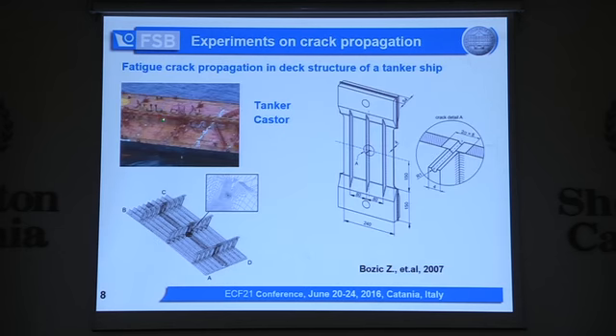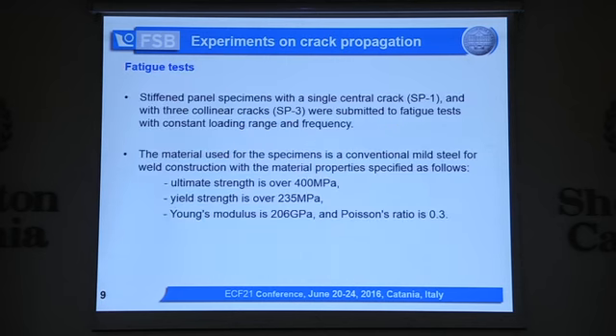And to mimic what we have in the deck structure of a ship, this situation here, we designed a specimen which looks like this. It's a plate with welded stiffeners, and here we have a cut stiffener and a crack which is already in the plate, and it looks like this. So we consider basically two situations: a single crack damage and three cracks at each stiffener. Today we speak more about this, but we will show you experimental results for both cases. A simple specimen with a single crack, SP1, was considered, and one with three cracks.